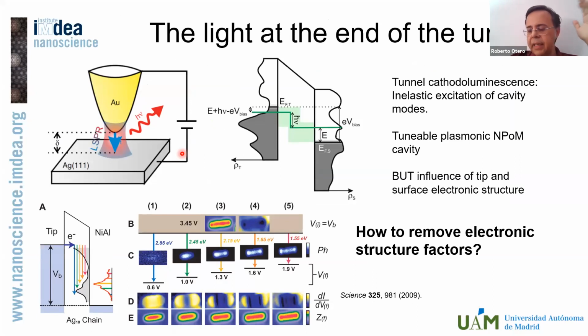While it is clear since the 70s, actually, that inelastic tunneling is involved in the excitation of localized plasmonic modes, so that electrons flow between, say, the tip and the sample. They lose a little bit of energy in between, and this energy is actually used to excite the localized surface plasmon resonances, which later on decay radiatively.